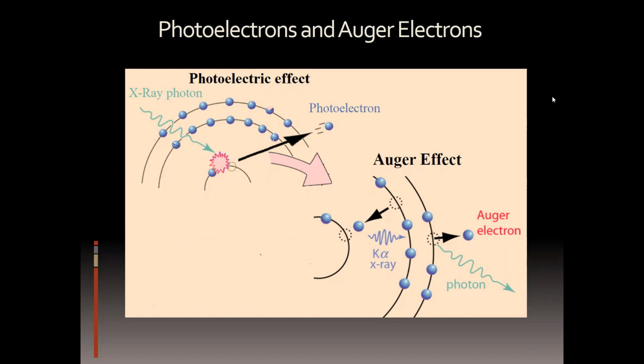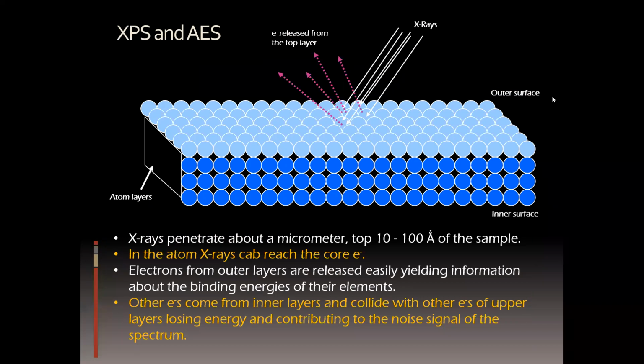So we can use the photoelectron to identify the element, but also we can use the Auger electron. The advantage of the photoelectric effect is that you get many more compared to these, because not all the time this photon that is produced is absorbed by another electron. So we have those two processes. And because we're dealing with X-rays, the X-rays will hit the surface of the material. They will not go too deep, say anywhere between 10 and 100 angstroms. But in any case, they will be able to reach just about any electron in the atom.